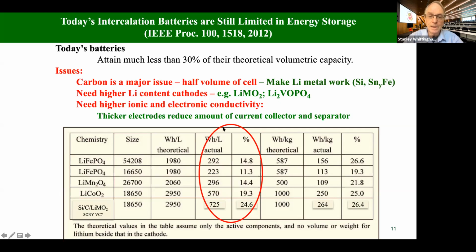And you can see some of the numbers here, don't worry about all the details, but this percentage here is the percentage the actual battery gets of its theoretical volumetric capacity. So it varies from 11% to close to 25%, and the gravimetric is around about 25%. So it's still huge opportunities for improvement. And I'm part of the DOE Battery 500 Consortium, and our goal is to get this number up to 50%.